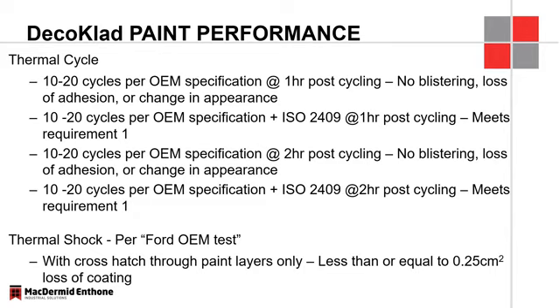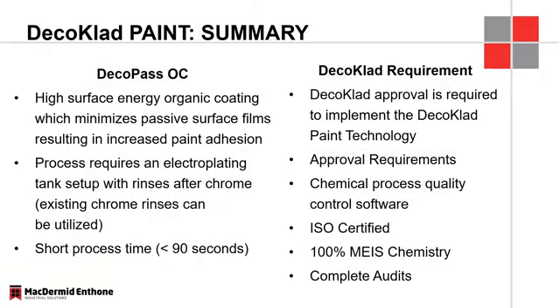Thermal cycle and thermal shock are probably the best way to determine if you have a viable paint on chrome process. It is not easy to withstand 10 to 20 cycles, again, depending on the OEM specification, and then going through water, with no blistering, or sometimes these finishes would just shear right off the surface. So very stringent tests for thermal cycle and thermal shock when it comes to meeting these OEM requirements. And we've been able to do that successfully.